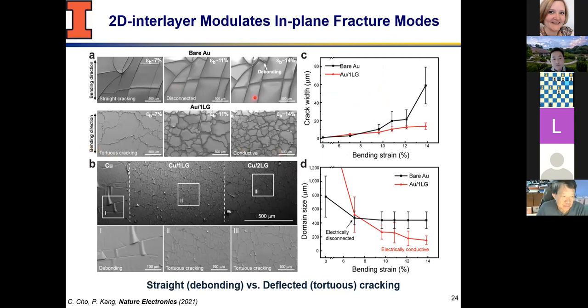Here are some fracture surfaces of bare gold, or gold with, I think in this case, titanium chrome underneath, on PDMS: straight cracks. Whereas when you just put a single layer graphene, you start to see these irregular domains and they start to break into smaller domains as you keep increasing the bending strain. And you can analyze these in many ways. Something we have done was the width of the crack. So that's the width between the two domains, or the domain size of your individual domain, averaging number.